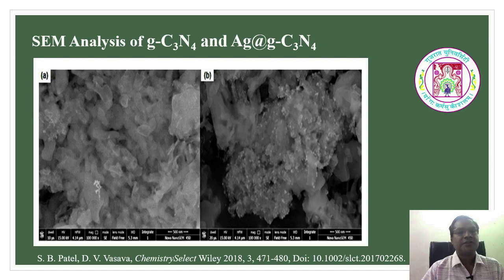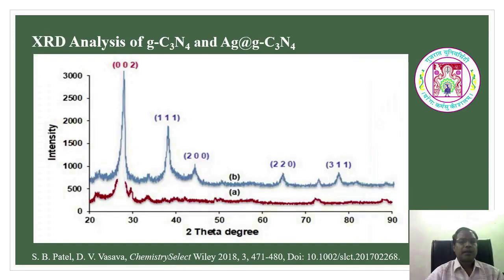SEM analysis is utilized to study the surface morphology. So here this is the SEM analysis of Ag nanoparticles supported on graphitic carbon nitride. In figure A, it is the SEM image of the graphitic carbon nitride. It looks like a flower. Now when Ag nanoparticles are doped on the supported carbon nitride, a rough surface is seen, that is figure B. So here it confirmed that the Ag nanoparticles are doped on the support.